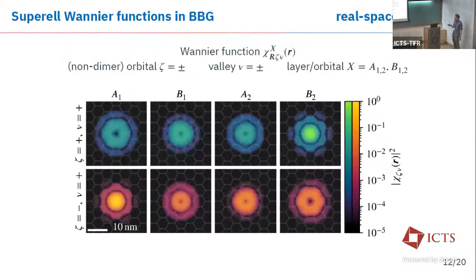For the two Wannier functions, we now have a degree of freedom on the orbital basis. They can either be localized on the B2 or the A1 orbital, corresponding to the leftmost lower A site of the lower honeycomb lattice, or the rightmost upper B site of the upper honeycomb lattice. Of course, they have some weight on the other sites as well, but notably this is a logarithmic color scale, so we really see that those Wannier functions are strongly localized within or around one or two supercells. The honeycomb you see here in white is the superlattice, or the supercells.